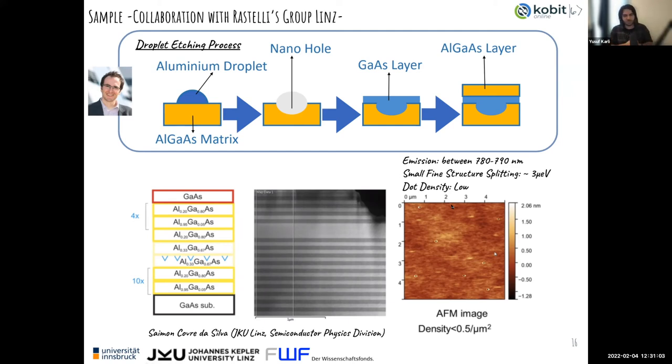These quantum dots are good in density but they are not very bright because these epitaxially grown quantum dots are embedded in semiconductor materials. Total internal reflection of the emitted light at the semiconductor-air interface may lead to less than one percent extraction efficiency even with high numerical aperture optics. But using distributed Bragg reflectors, DBRs, and solid immersion lens on top of the surface, we could increase extraction efficiency to approximately 10 percent. However, now we are also working on different hybrid samples structured with collaboration with Armando Rastelli's group and some bullseye cavities like Luca Sapienza did in recent years to improve extraction efficiency.